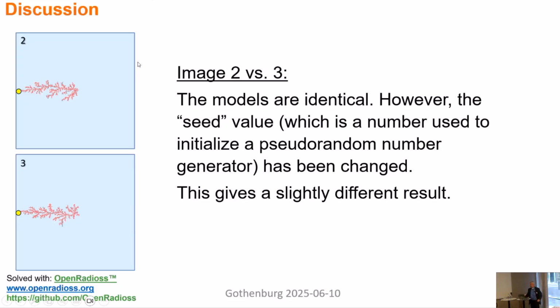And here, if you repeat, with no change in the model, but just run it twice, you see, for example, here or here, there are slight differences in the results. Tiny differences, but there are differences. If you now do several repetitions of this run and change the seed values for the random number generator, you can do robustness investigations of part of your system, to check how robust the design will behave, because the pattern will always be slightly different. But again, we still define the starting point and the ending point, which is in the middle.